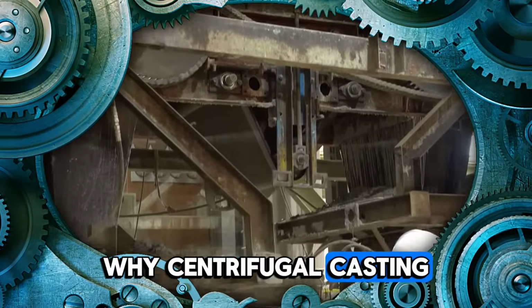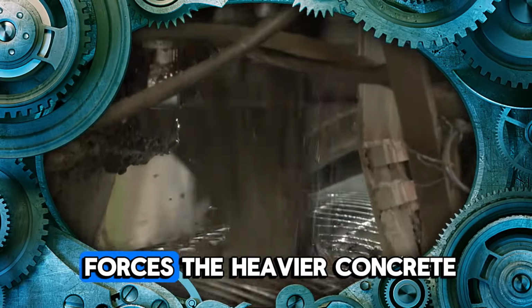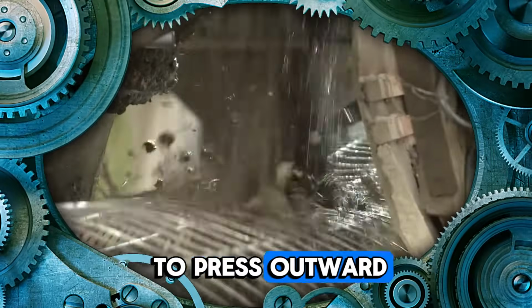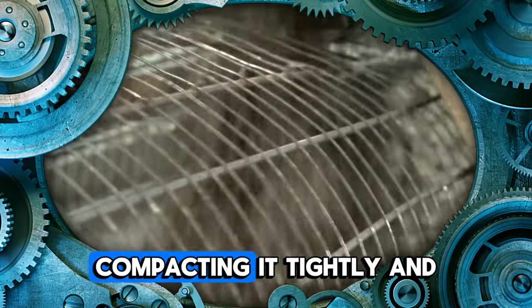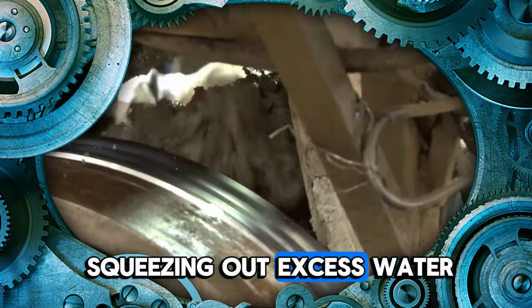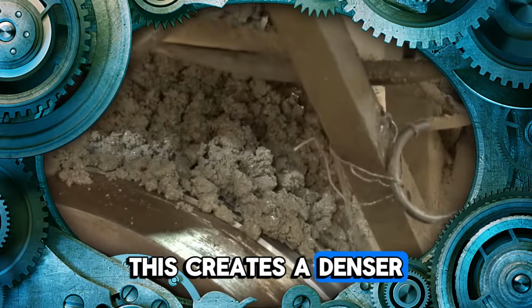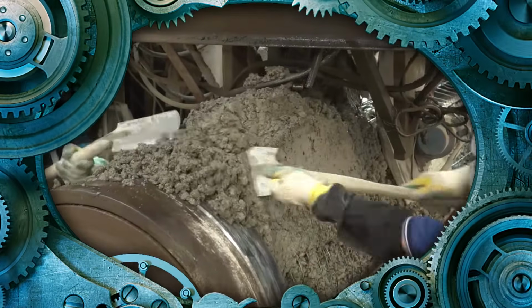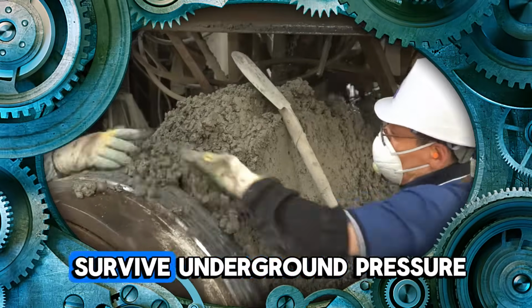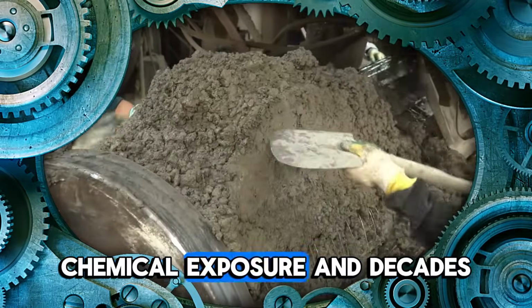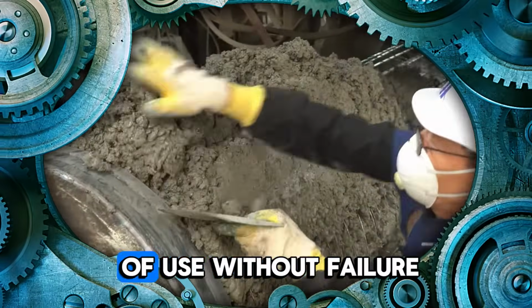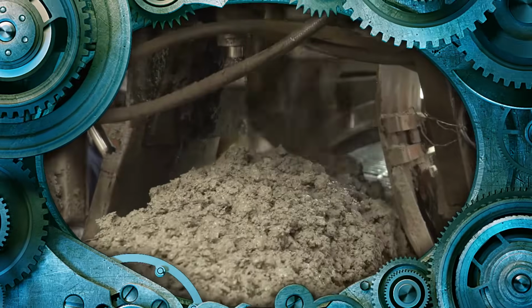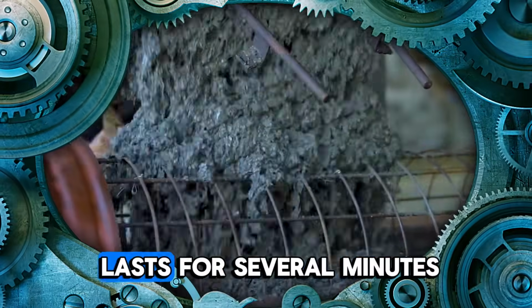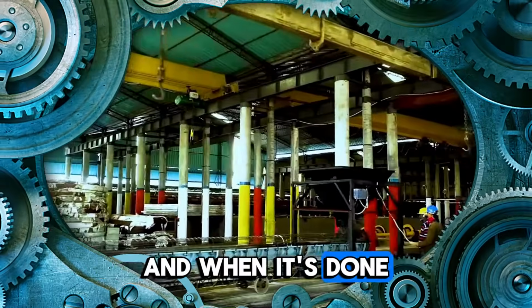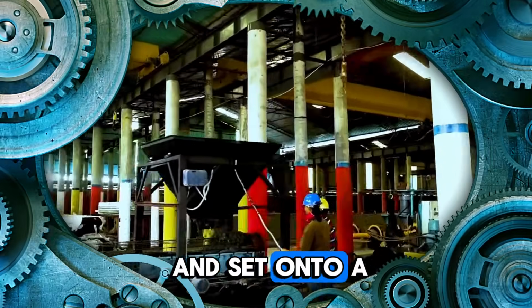Why centrifugal casting? Because spinning the mold forces the heavier concrete to press outward toward the mold wall, compacting it tightly and squeezing out excess water. This creates a denser, stronger outer layer. That layer is what allows the pile to survive underground pressure, chemical exposure, and decades of use without failure. This high-speed spin lasts for several minutes, and when it's done, the mold is removed and set onto a long curing rack.